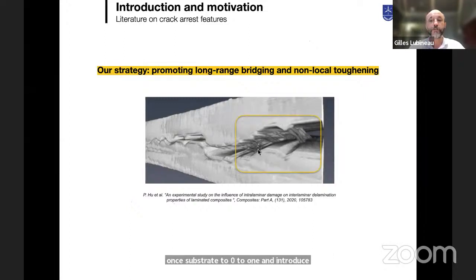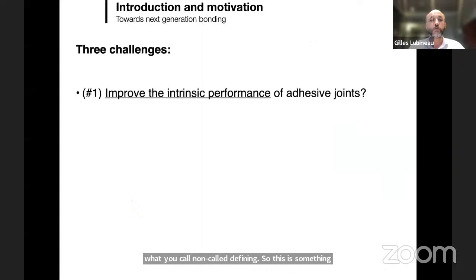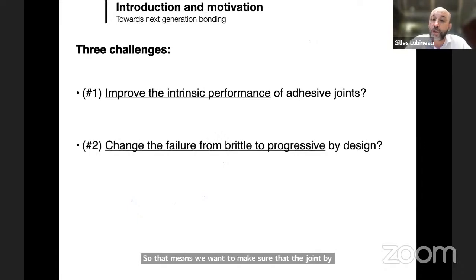This is important for us, because what we want to do is, in fact, to improve three things. The first thing is that we want to improve the intrinsic performance of the adhesive joint. That means we want to make sure that the joint by itself is going to be tougher. We want to change the failure of the joint from being brittle to a progressive failure by design. That means we don't want to have unstable delamination. We want to stabilize this.